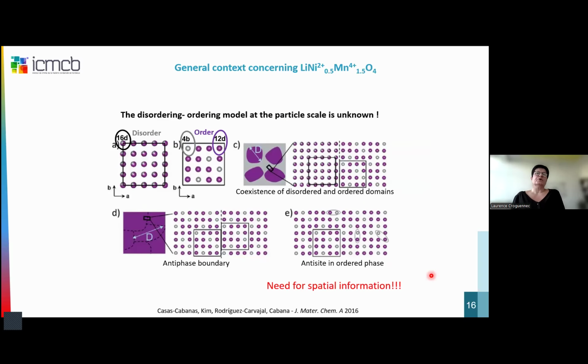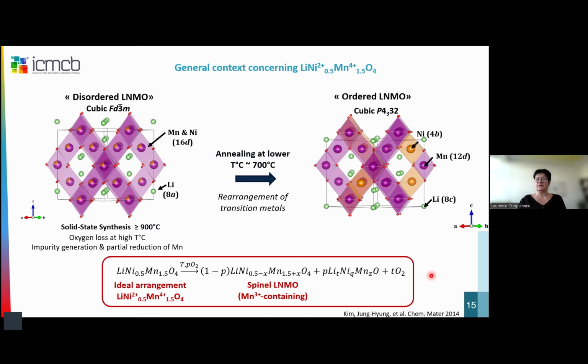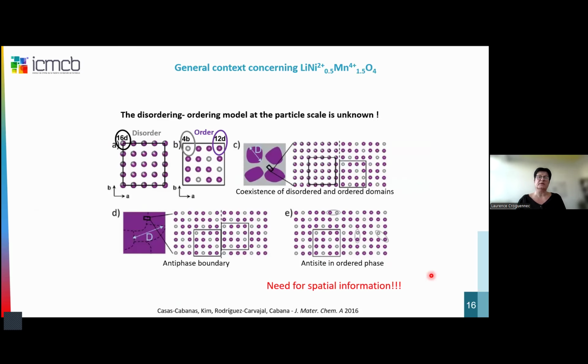And then the other question here, when we speak about ordered and disordered structure, was also addressed by our colleague Montse Cabanas and co-authors in 2016: in fact, we are not really able to describe exactly how this order and disorder is organized at the particle level and even at the powder level. You see here, in the a,b plane in these materials, disorder is described with this statistical distribution on the 16D sites of the nickel and manganese. When we move to the ordered, we have again this 4B and this 12D.